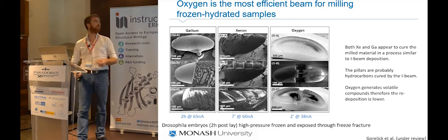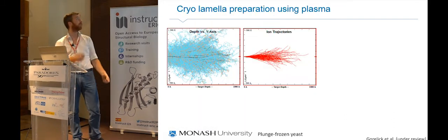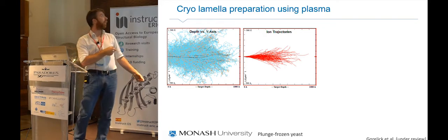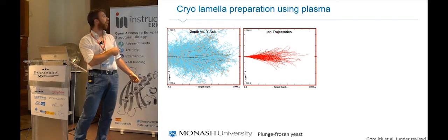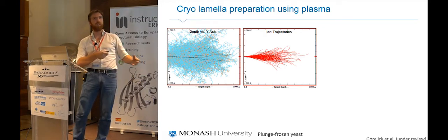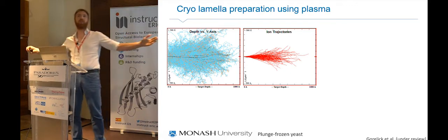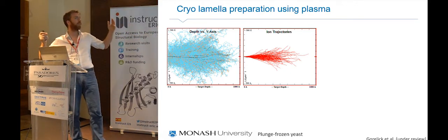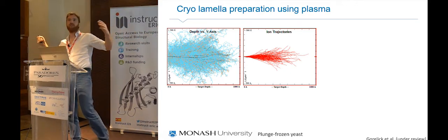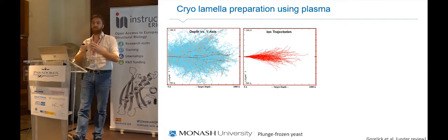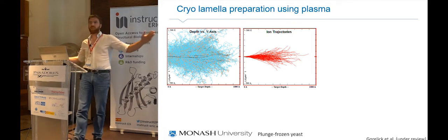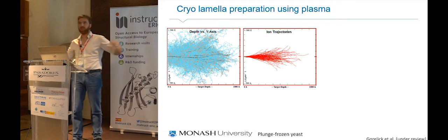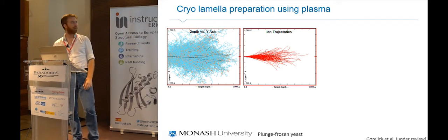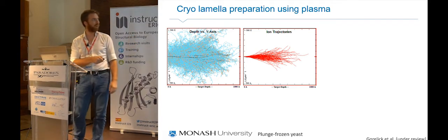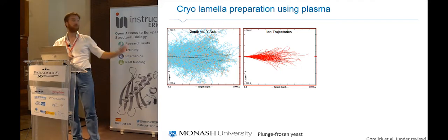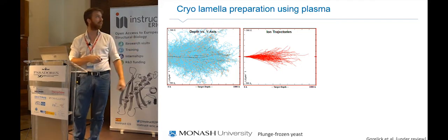We can do lamellas with oxygen. No, because physics is a bitch. The reason is that you have an ion that comes in. The lighter it is, the more it struggles into the material, and therefore you're damaging. So the take-home message is, if you've got a very light atom, you will damage a lot on the side, and if it's a high energy, it will damage even more. This happens also with gallium, and this happens with everything. It's just that the heavier, the lower the damage.